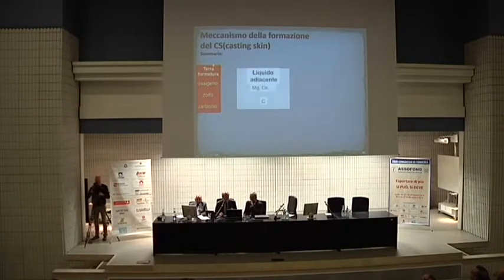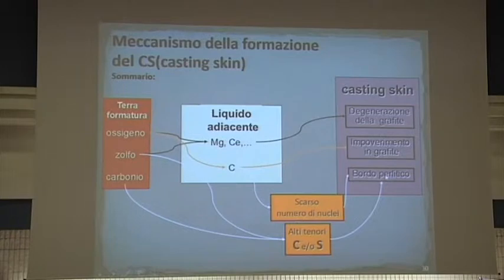So in summary, in the molding sand you have oxygen, you have sulfur, and you have some carbon. In the adjacent liquid you have carbon, magnesium, and cerium. And the sulfur and the oxygen will react with the magnesium in the layer at the interface and will result in degeneration of graphite. Oxygen will oxidize the carbon and it will remove graphite. And it will also remove the nuclei for the solid transformation, and therefore will form a pearlitic border. And the carbon may result in increasing the carbon content in the superficial layer and give you a pearlitic border.